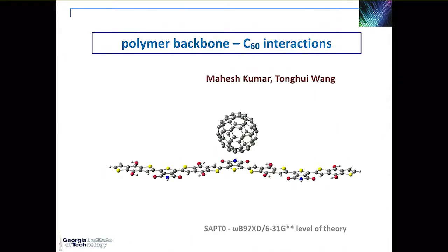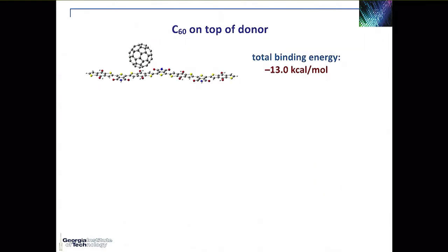But as we started to do that, we realized, and that's a couple of years ago, that there had actually been very little done in terms of characterizing the binding of a fullerene and the polymer chains. So we started to look at those polymer C60 interactions, and in order to go into increasing steps of complexity, we started with having no side chains on the polymer and no side chains on the fullerene. So it's just C60 with a long oligomer having no side chains. And at the level of the calculations that we used, you get fullerene-oligomer binding energies on the order of 13 kilocalories per mole when the fullerene optimizes its position on top of a donor part of the oligomer.